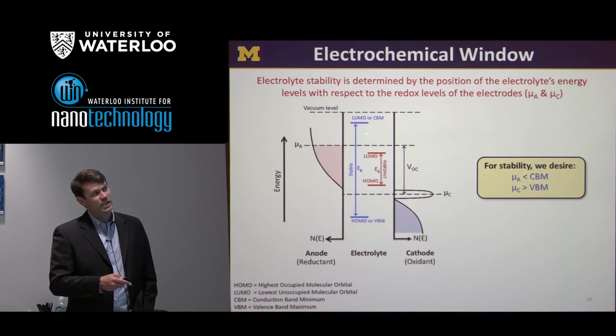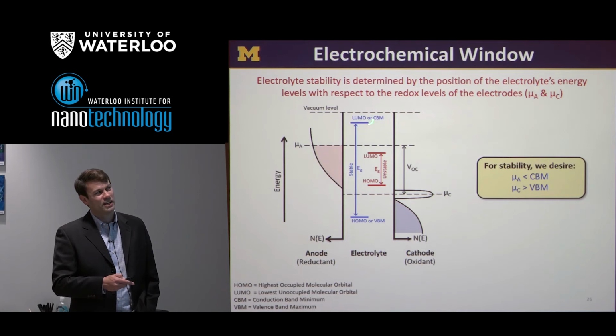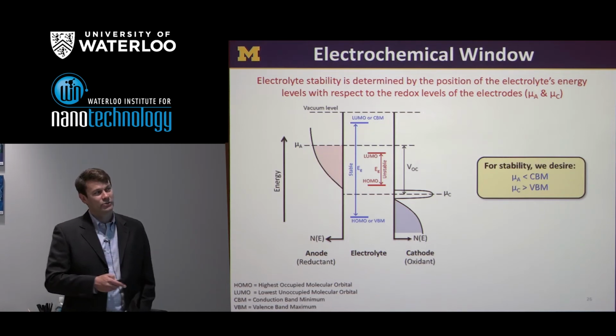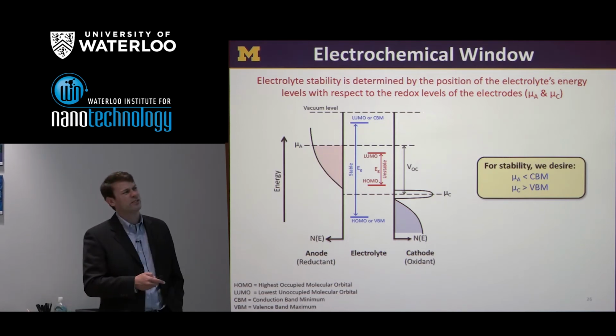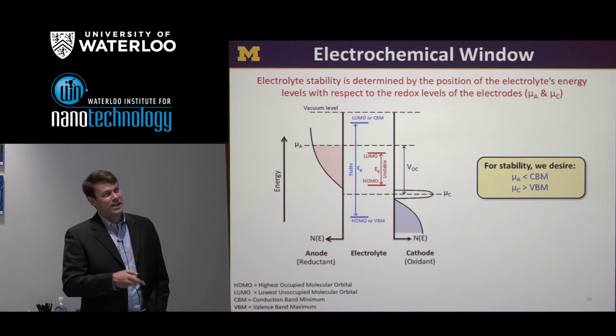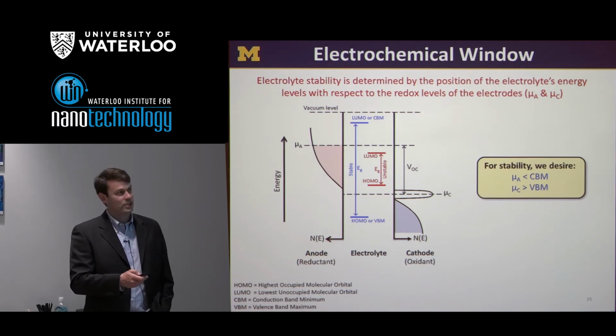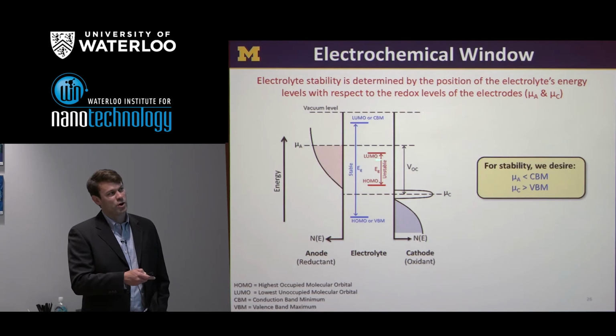And so for stability, what we would like to see, for thermodynamic stability, is that the LUMO, this unoccupied level, should be higher than the electrochemical potential of the negative electrode. In many conventional lithium-ion liquid electrolytes, for example, the LUMO of the solvent is actually below the mu A of the anode.